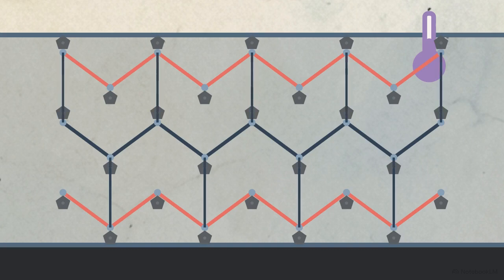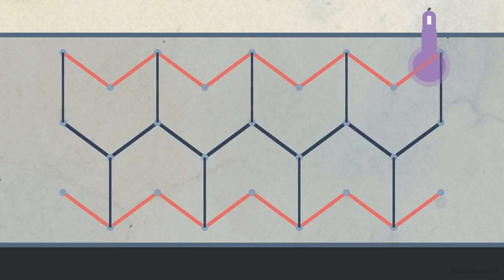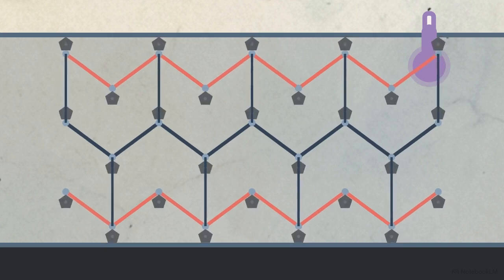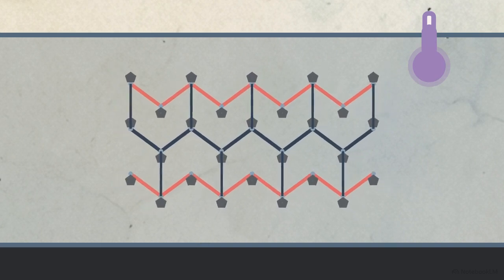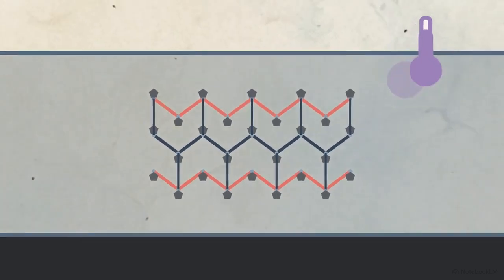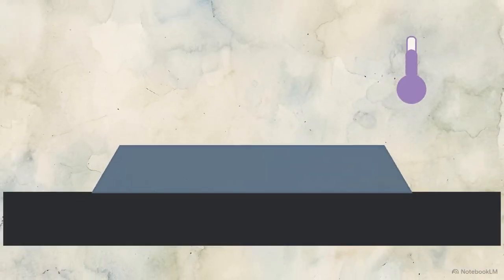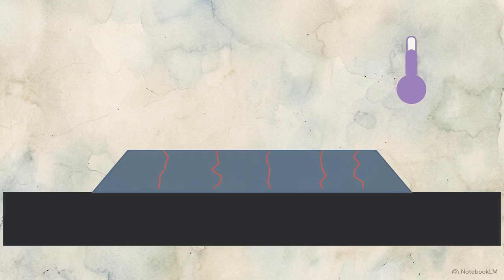This polysilazane network highlights the silicon-nitrogen and silicon-oxygen backbones. Low-temperature cross-linking forces chains to branch, locking into a solid matrix. Pyrolysis drives off organic molecules, causing mass loss. The remaining lattice compresses, pulling against the substrate, forming microcracks.